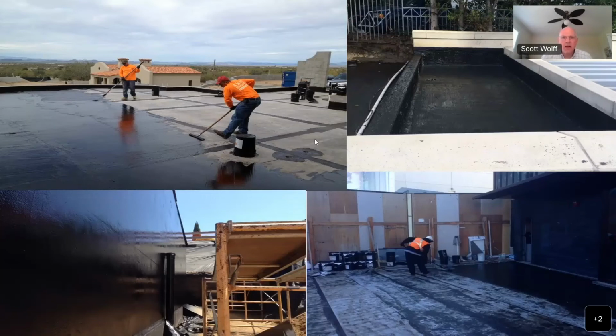Actually, this looks like hot applied rubberized asphalt. So we typically go 90 mils, reinforcing fabric, 125 mils, and then roll out the protection layers. So, but again, we always ideally want to have contractors installing these types of systems recognized or authorized by the manufacturer.